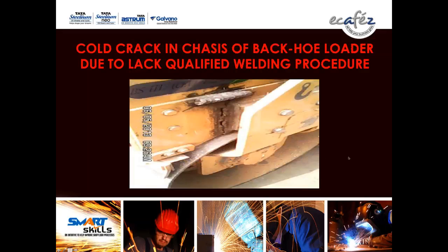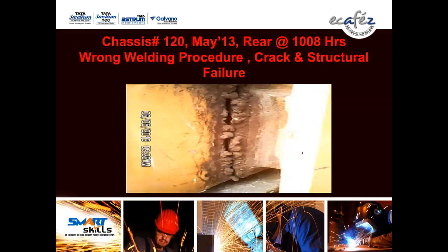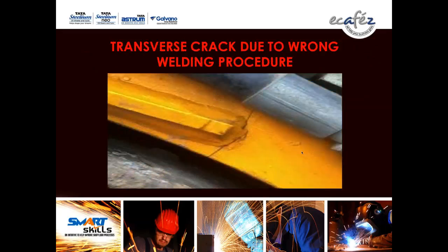This is a picture of cold crack in a chassis of a backhoe loader due to lack of qualified welding procedure. This is also a structural failure and welding failure. The crack is due to lack of proper welding procedure and lack of a proper welder. So this should be avoided. Transverse crack due to wrong welding procedure. Check in the pictorial view, transverse crack in the fillet joint. This is due to lack of welding procedure.